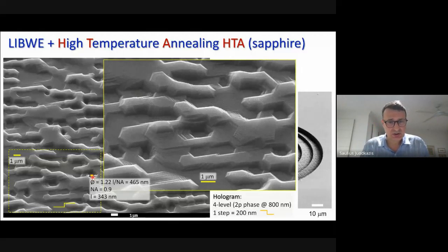Ablation spot is shown here. It's really a very tiny, tightly focused focal spot, used to do laser ablation, and it was micro-nano rough. But after annealing, it becomes atomically smooth. You can recognize the C-plane of sapphire, but what is important is that the design height was not changing. It means that we can create optics which is as designed with the steps, and it is atomically flat.